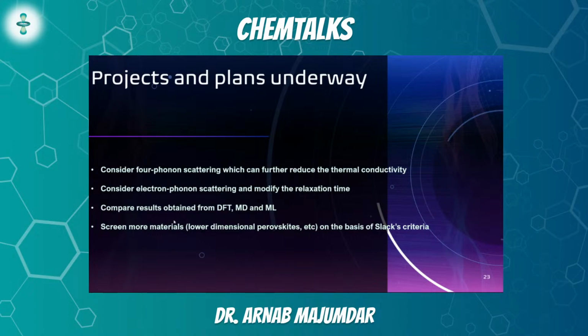And lastly, based on Slack's criteria and not based on hit and trial, because if we go through a high throughput methodology, it's kind of like a hit and trial where we keep on filtering. But if we want to use real scientific background and on the basis of the Slack's criteria, we are trying to screen more materials with lower thermal conductivity. And some of these materials would include lower dimensional perovskites. We already know what perovskites are, but perovskites can exist in different dimensions as well. So we're looking for lower dimensional perovskites following Dresselhaus's proposal that if we lower the dimension, the thermal conductivity will decrease. So that's what we are currently doing.